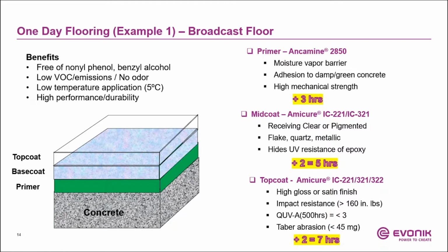The benefits here with the whole system, again, the purpose is to protect the applicators and the occupants of the space that you're applying the coating. The benefits with these systems are it's free of nonylphenol, benzyl alcohol, which again it can emit over time. So low emission technology, low VOC technology, and these can cure at even down to 5 degrees Celsius, so low temperature. Of course, the return to service will be slower, it will take longer, but they do cure at lower temperature. And then your resulting coating is really high performance, high durability.